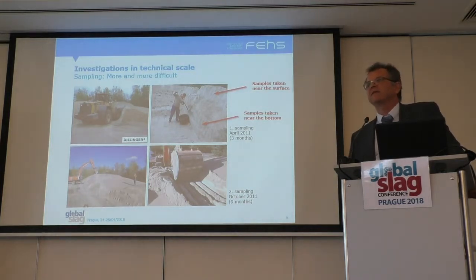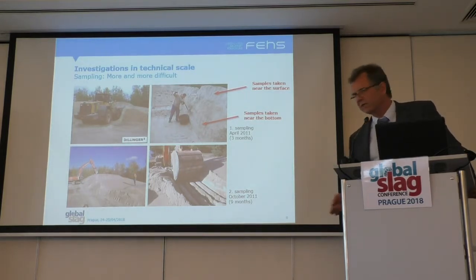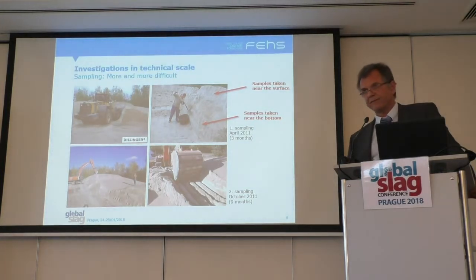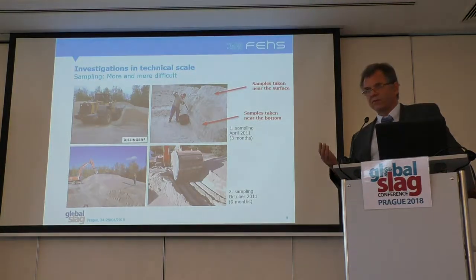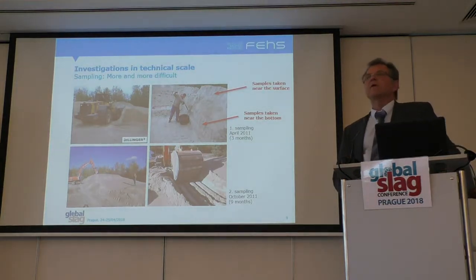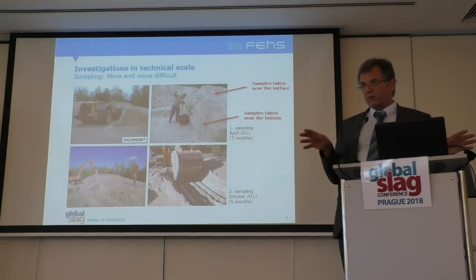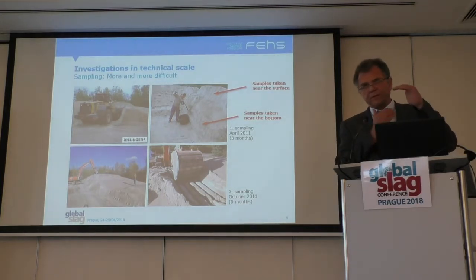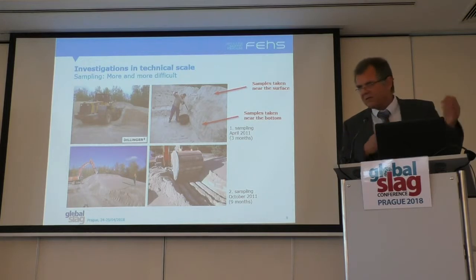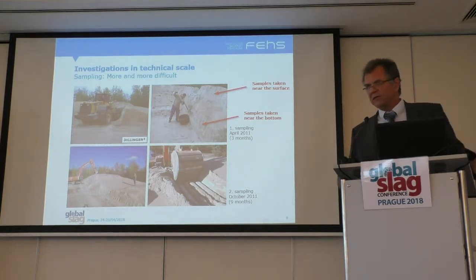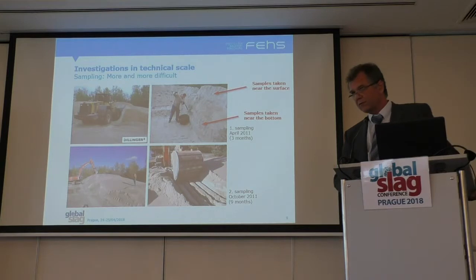It's coming from the slag itself. If it is leaving the steel plant, it will have maybe 10%, sometimes more, sometimes less, water content, and the slag is more or less porous. And the water which is in the pores will not come out independent from the conditions in the main part of the stockpile.